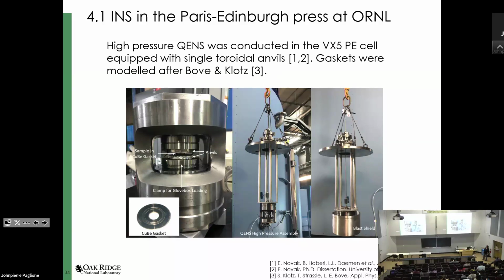So typically the sample would be here in the center, but for the QENS we put it here in that ring. So the sample was in here. Our first experiment was something hydrogenated, which is why we wanted the sample very thin. So here you see the setup of that Paris-Edinburgh press. That's a smaller one, a 150-ton press. On that long contraption, this is how it went down into the BASIS beamline.